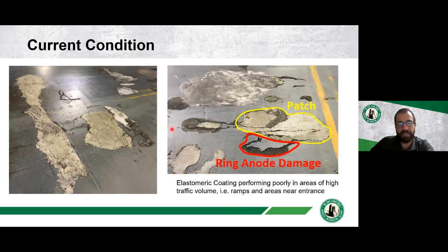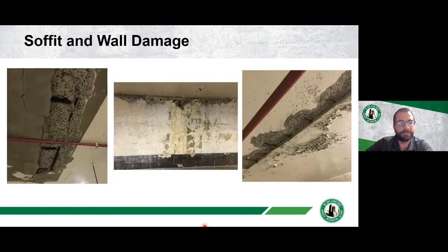You can also see that there is a coating on the driving surface, an elastomeric coating. There was also some damage on the underside, so you see some soffit damage. We see rebar corroding. This is an old patch, and we have corrosion in that patch, so maybe that patch wasn't done very well. The wall, we're below grade, so we're seeing water transporting through the walls, causing corrosion. And then at a construction joint here, we see leaking through the joint and then corrosion of the reinforcement at that joint.